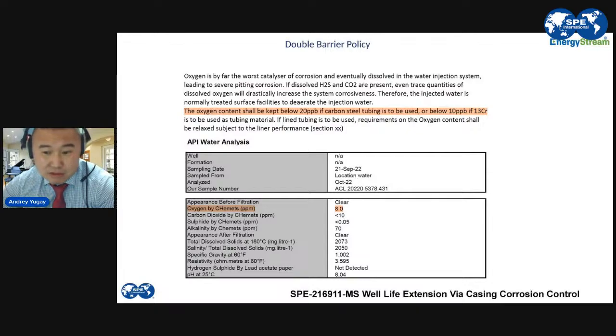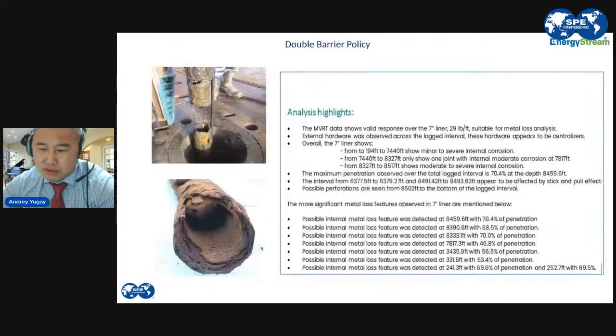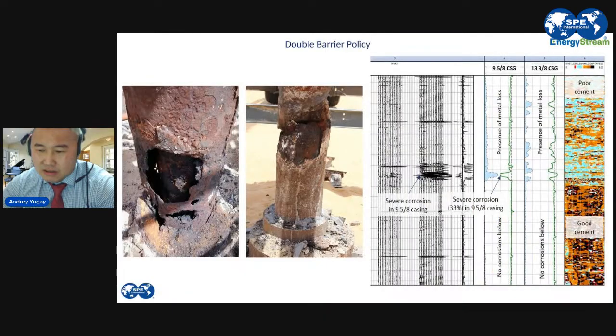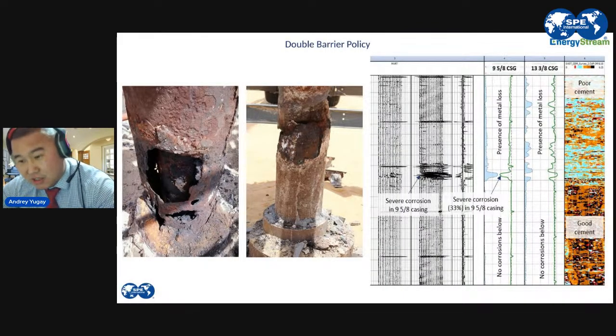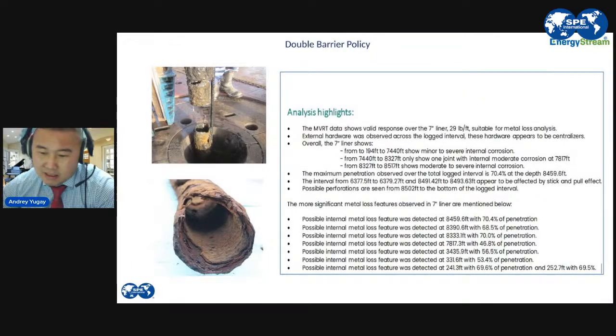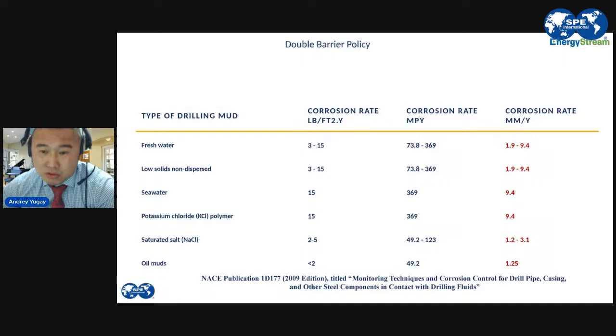So this can be controlled with the usage of chemical corrosion inhibitors, biocides, oxygen scavengers. Such kind of corrosion on the right side could be prevented if we control our fluids that get contaminated with the cement slurry and get trapped. And you know, stagnant conditions could be even more dangerous than dynamic in terms of corrosion.